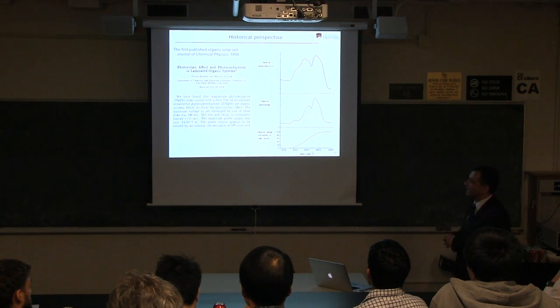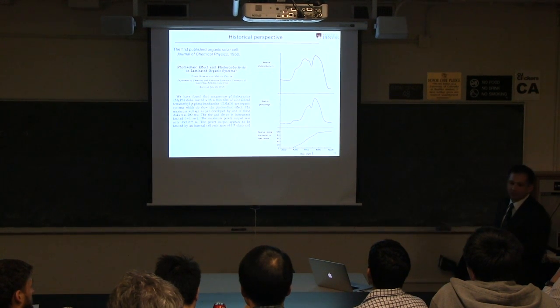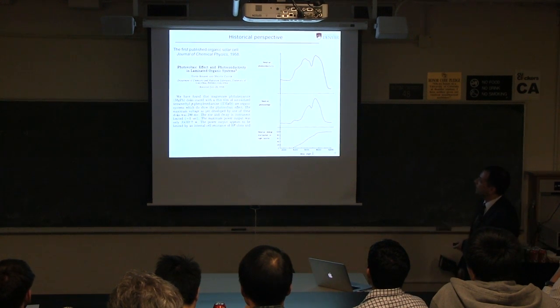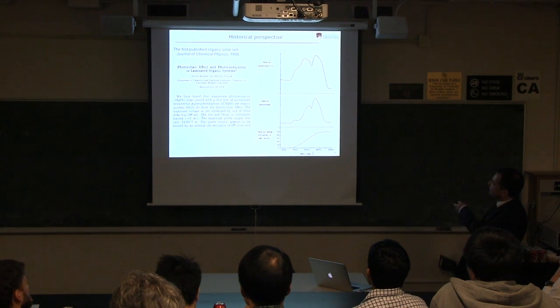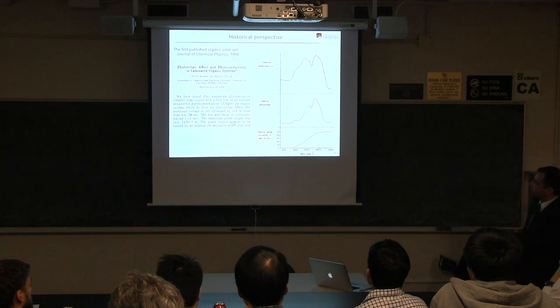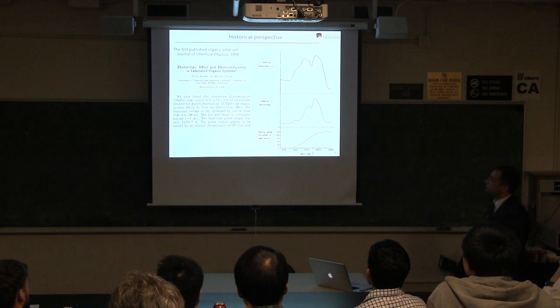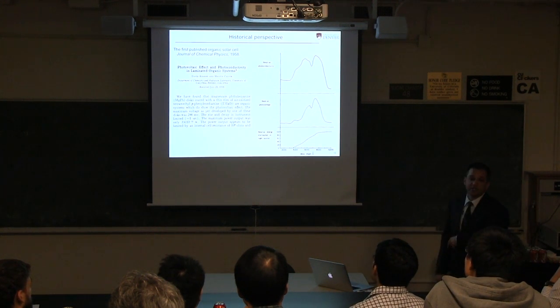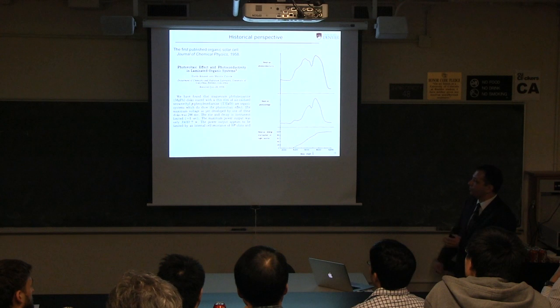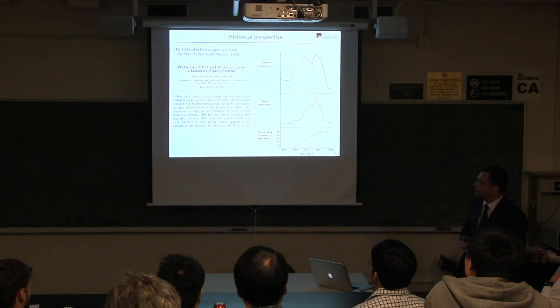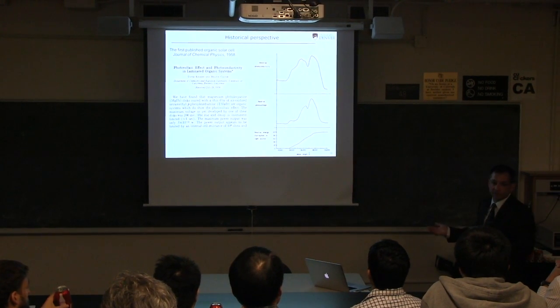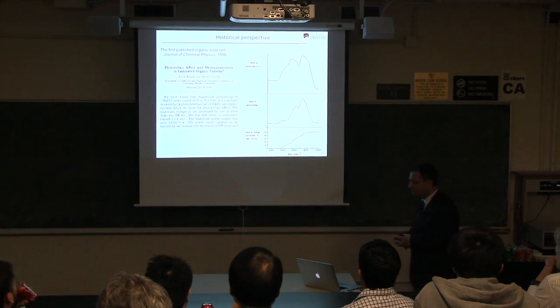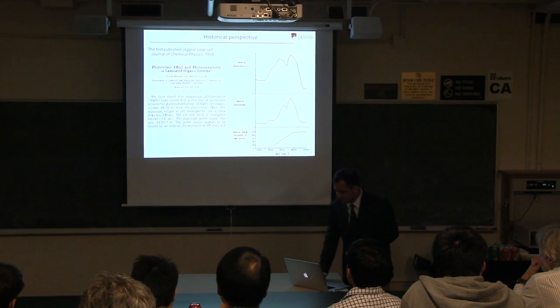There was a problem. They didn't know at the time that both of these materials are essentially p-type. So they had a heterojunction, but it wasn't a true p-n heterojunction. Nonetheless, it worked. What was interesting is they got photo response out to past 900 nanometers, which even today we have trouble getting efficient response out there. And what was also interesting is they fabricated it by lamination. So there's no vacuum deposition involved. They simply laminated these 2 layers together. And that's something we actively research today, laminated production. So it's quite cutting edge, at least for the time.